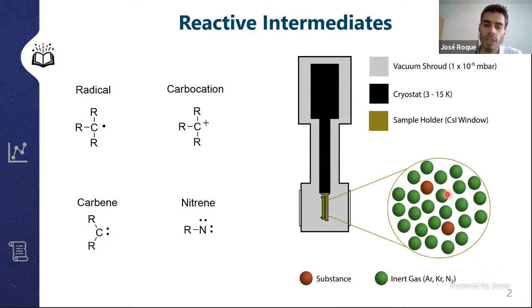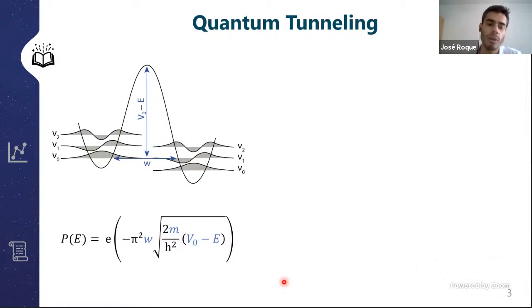The point with matrix isolation is to prepare a sample where the substance being studied is completely surrounded by an inert gas like argon, krypton, or nitrogen. Also, this sample is prepared at extremely low temperatures, close to 0 Kelvin. But still, some of these molecules were found to undergo chemical transformations, and they do so by a mechanism called quantum tunneling. Basically, quantum tunneling predicts that a molecule held in a deep well can actually penetrate a potential barrier to a different state, even though it lacks enough thermal energy to overcome the barrier classically.